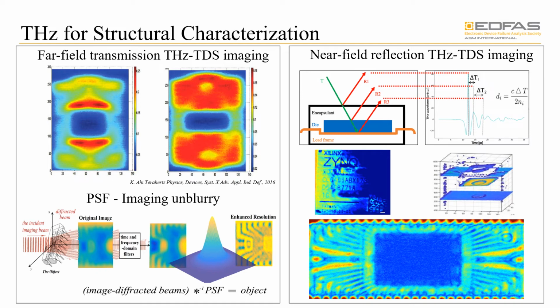Point spread function has been used to mimic signal propagation. By deconvoluting the PSF onto the original image, the image resolution can then be dramatically increased and have the potential to be used to characterize the more small-scale elements that are seen, such as in the heterogeneous integrated packaging. Another way to increase the resolution of the images is by using the near-field detection method. The near-field detection usually refers to the sub-wavelength detection, which will eliminate the free space diffraction problems.